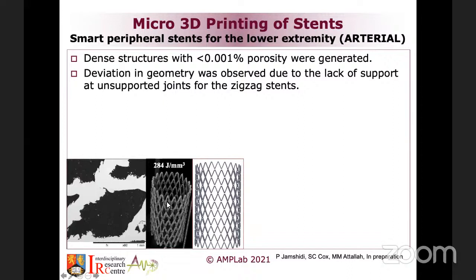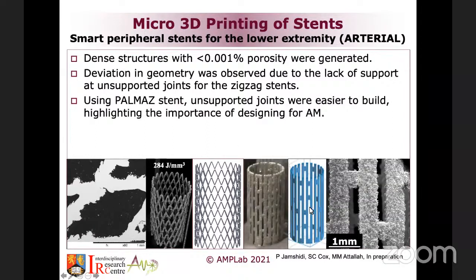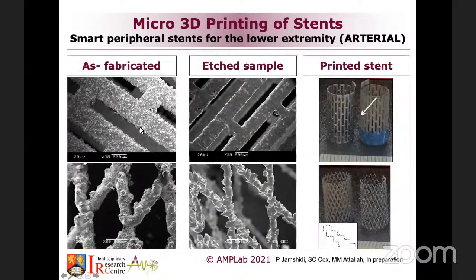If you print a shape like that, the zigzag shape, you may get some non-uniformity in the shape. But if you print some other geometries, you can get easier stents. Yes, you still have unmelted particles on the surface, but these unmelted particles can then be cleaned to create a more uniform stent. So what we have been doing is using chemical etching to clean the surface, and we found that that again depends on the geometry. So if you print a straight stent similar to that one, with etching, you can clean up the surface and generate a nice looking stent like that one.